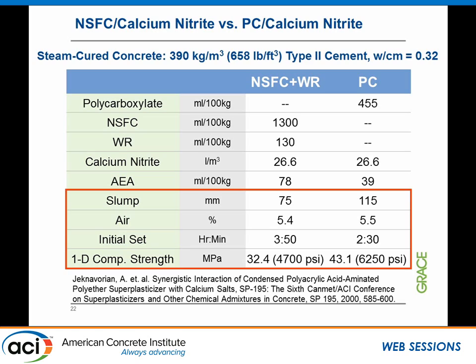This is a Portland cement mix. It's a type 2 cement where we were using naphthalene sulfonate as a water reducer in one mix versus a polycarboxylate in another mix. In both mixes, we use calcium nitrite and some air entrainer. And the results in here are really quite interesting. In terms of slump, we got higher slump with the polycarboxylate. Air, we were able to manage at equal level with the adjustment of air entrainer. Initial set, definitely a lot less when polycarboxylate is used with the calcium nitrite. And we also realized a lot higher strength. So there are some synergies that we are seeing between the polycarboxylate and the calcium nitrite.